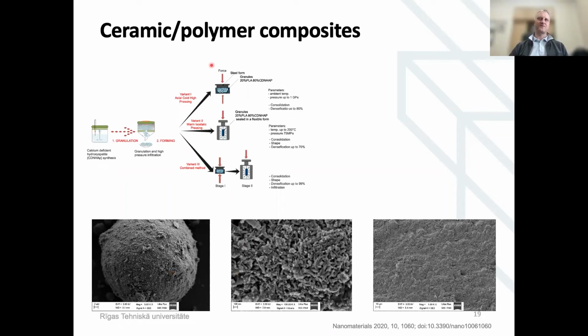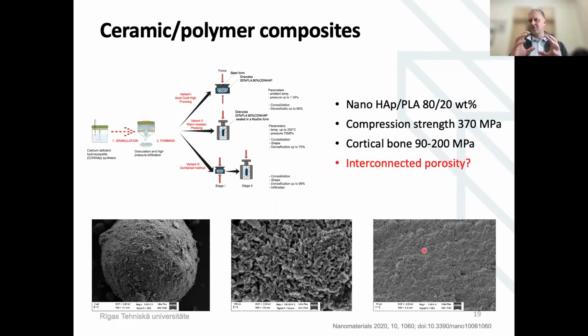So trying different kinds of consolidation methods, again applying the temperature and applying the pressure, we achieved really nice densification. And looking as a material scientist at the properties, we have more or less the chemical composition that is close to the bone. We have compression strengths which are almost double that of the cortical bone, which is really amazing. So we were very lucky for that. But again, we are able to produce it dense, but not yet with interconnected porosity. So this is one of the fields we should focus on. We have some ideas how to do it, but that's probably the task for some of the forthcoming projects.